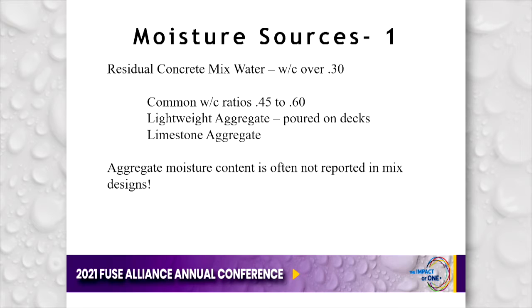So let's start with what I'll call moisture source 1, and that's the residual concrete mix water. It takes about 3/10 of a pound of water to hydrate a pound of cement. At that point, we have something akin to Play-Doh. We couldn't do much with it. So common water cement ratios are going to be between 0.45 and 0.60. It becomes readily apparent that even at 0.45, which is a good water cement ratio, we have 50% more water than we required in order to hydrate that cement.